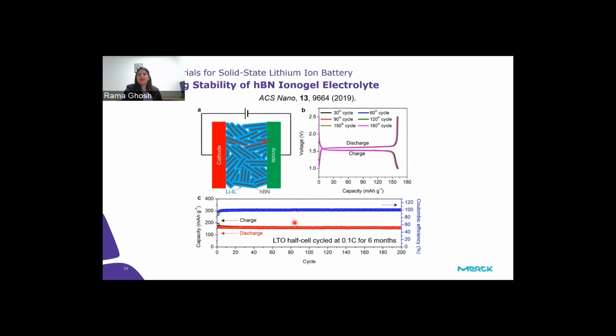Here you can see the cell; maybe the cycle rate is a little lower because when we first synthesized it, the size was a little bit higher, nearly 100 micron. It's thicker. We later worked to make it thinner and got good performance as we expected.